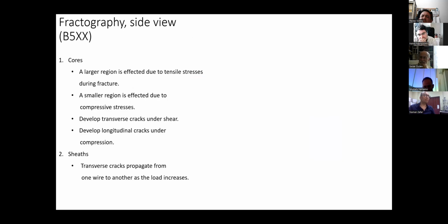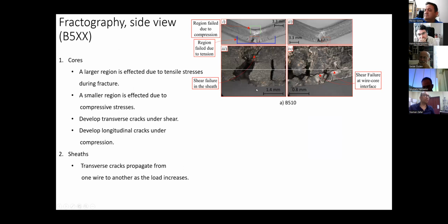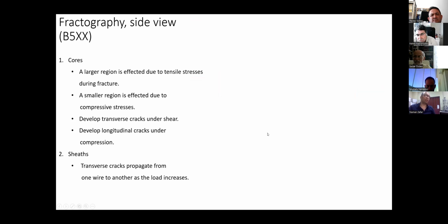Here is a specimen which has larger cores. Again, we can see that the sheath and core interfaces fail in longitudinal cracks, but the cores fail in transverse cracks. The region which is under tension is majorly influenced by the tensile stresses in the bottom layer, but the region which is exposed to the compressive stresses is influenced only in a very small region by those types of stresses.